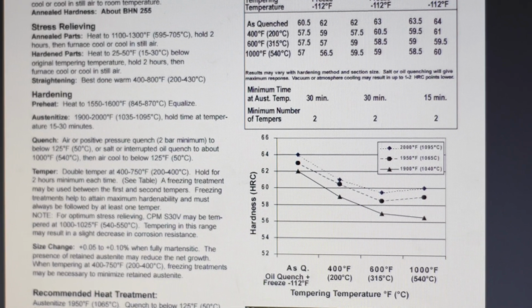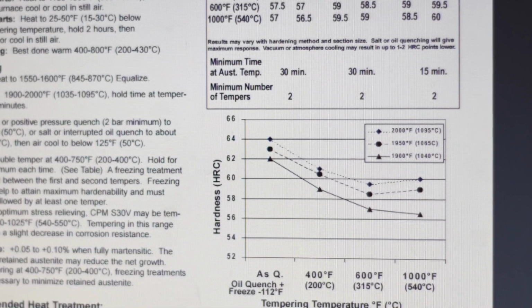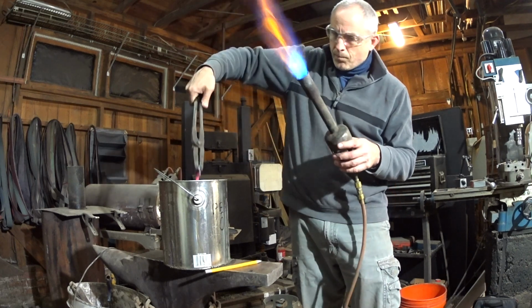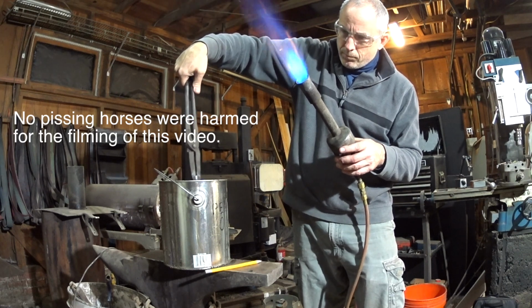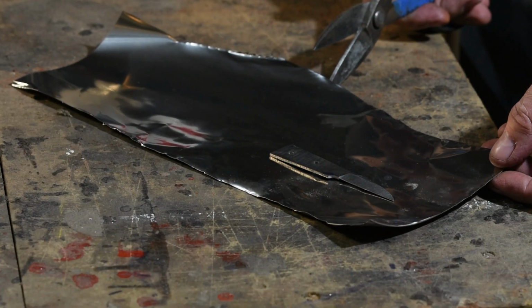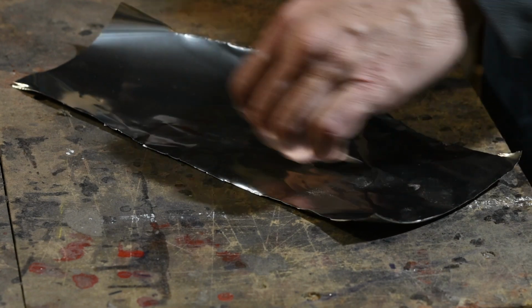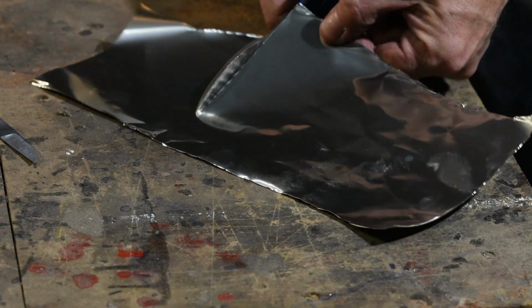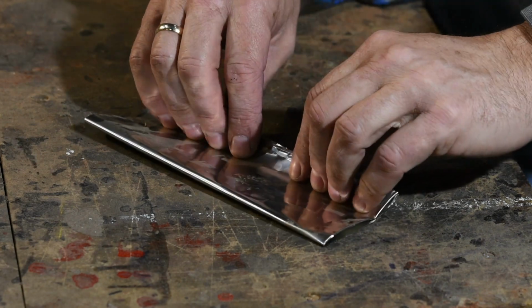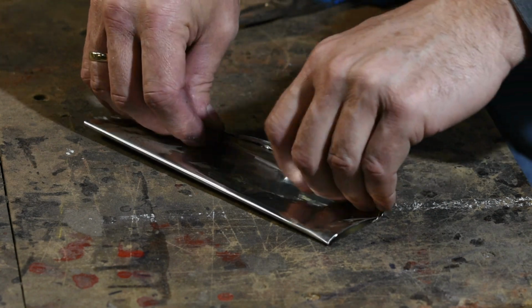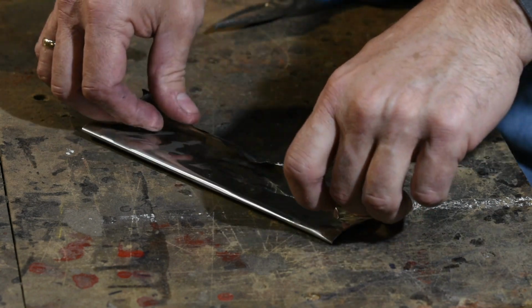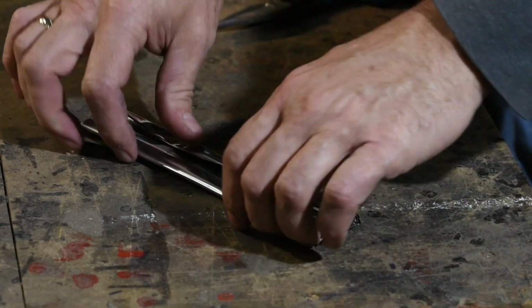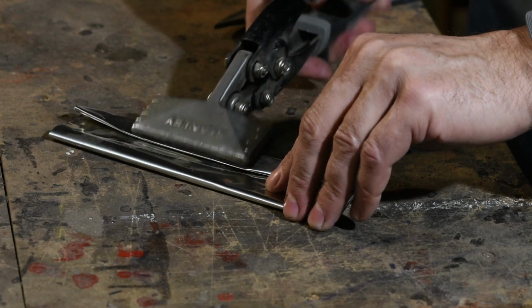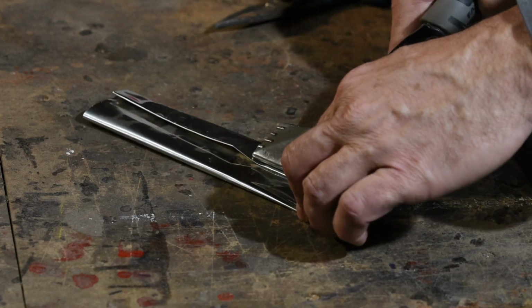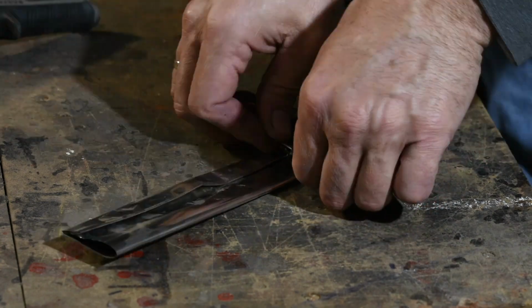There are sound and complex metallurgical reasons why you should follow manufacturers' heat treating instructions relatively carefully. The old heat it to cherry red and dunk it in a bucket of horse piss approach won't hack it with stainless steels. Because of the high heats and long soak times required for stainless steels, these steels have to be kept away from oxygen, which will leach out the carbon, create lots of nasty scale, and weaken the steel. In industry, they're typically heated in vacuum furnaces or in non-reactive gases or sometimes even molten salt. But we'll wrap them in stainless steel heat treating foil to shield them from the air. It's a little bit like folding up a razor blade. This stuff's really sharp, so you have to be careful in order to avoid cutting yourself.